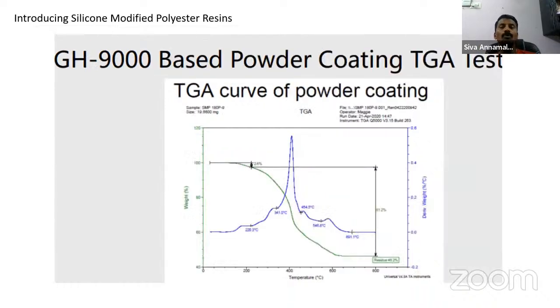Now, we compare how the polyester system behaves. That is a regular polyester, which is high viscous polyester. If you see the green line, from 200 degree, it's straight away coming down. It means at 300, 400, it's completely decomposed, and the residue is coming around 42%. This indicates the performance of silicone modified polyester is extremely good compared to your conventional polyester system.